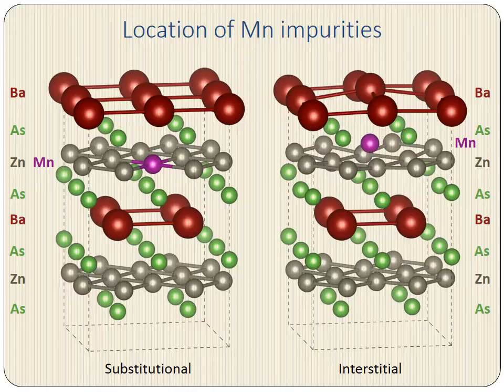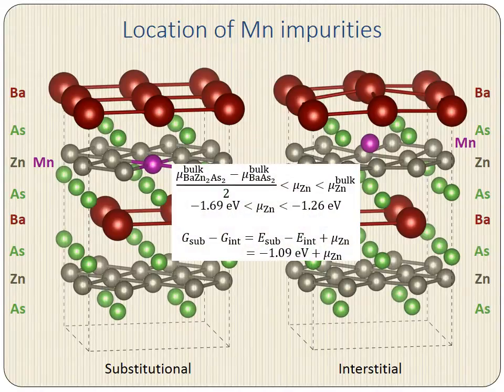Instead, we need to compare free energies. We can write down an expression for the free energy for each cell, and we obtain the following. We find that the free energy difference, using our calculations, is equal to negative 1.09 electron volts plus the chemical potential of zinc. The chemical potential of zinc can also be constrained with our calculations, and we find that it is in the following range.